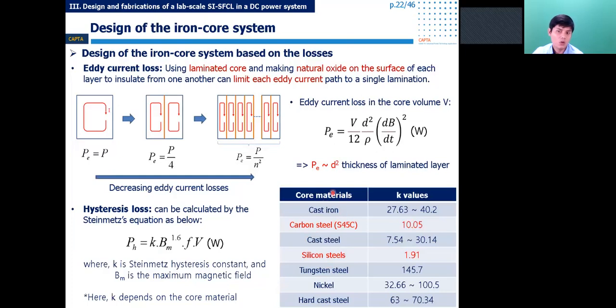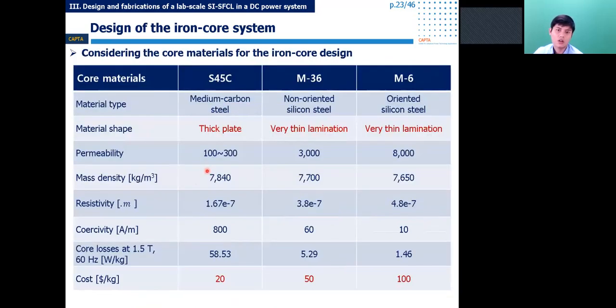In the first step, the iron core was designed to minimize the eddy current loss and the hysteresis loss. The laminated structure was selected to minimize the eddy current loss. In case of the hysteresis loss, we can select the core material like carbon steel or silicon steel to minimize the hysteresis loss. Considering the core material and the core properties, three core types, including the medium carbon steel, non-oriented silicon steel, and oriented silicon steel, were investigated and analyzed.